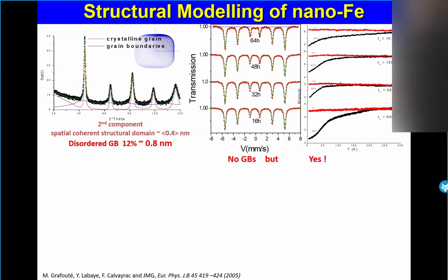So we made some X-ray diffraction, and the X-ray patterns were described by means of two components, better said, by three components. No, yes, three components because we have a background. But the two main physical components corresponded to crystalline grains and something rather disordered in between grains. In addition, it was possible to conclude that the grains were rather cubic. So now you have to pile different cubes, and in between you have the grain boundaries.